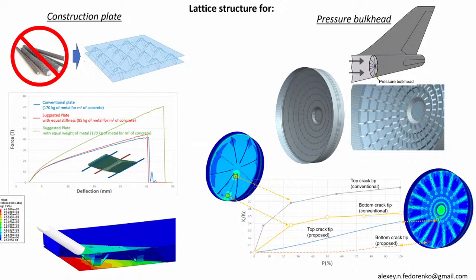And the second case is the idea to use a lattice structure for a pressure bulkhead of airplane. You can see the proposed structure, and we compare it with the traditional part. And the focus of this study is damage tolerance analysis. We assume that there is a crack in the structure according to some flight standards. And we found that using the proposed structure, the stress intensities with the lattice bulkhead are reduced if we compare it with a traditional one. This is in brief. Thank you.